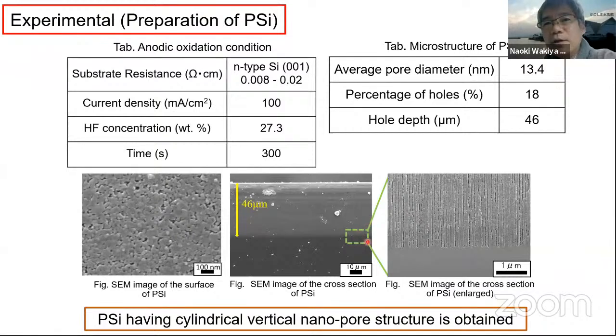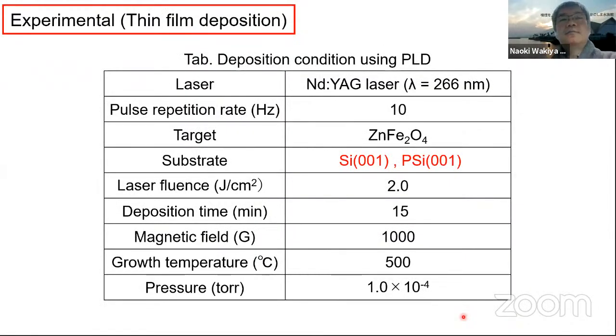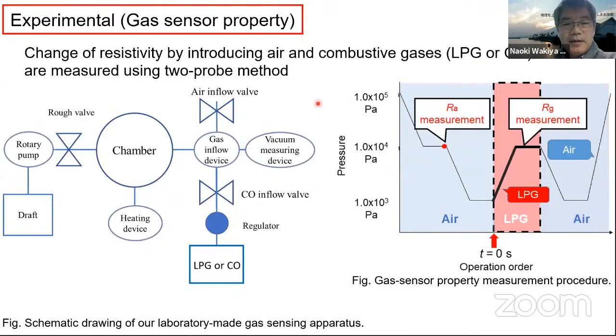And if we enlarge this area, we can see that cylindrical and vertical nanopores are obtained. The average pore diameter is around 13 nanometers. The percentage of the surface holes is around 18%, and the hole depth is 46 micrometers. So porous silicon having a cylindrical vertical nanopore structure is obtained. On this porous silicon, we deposit zinc ferrite thin film using pulsed laser deposition. After that, the sensor property is measured using a laboratory-made gas sensor apparatus like this.